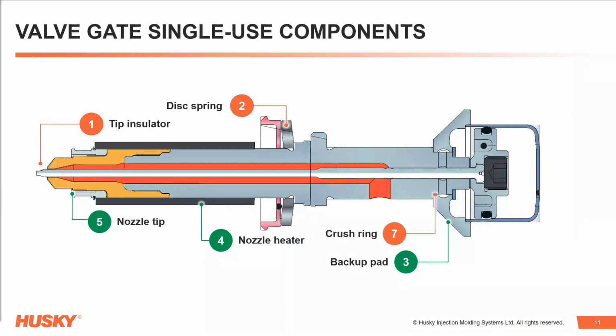The crush ring and the graphoil seal prevent air leaks. These ensure reliable performance for gate opening since excess air leakage can decrease efficiency, and they permanently deform when installed, and they cannot be reused. The piston seal is also a single-use part that should be replaced if removed. This controls the stem actuation in both directions. Age and excessive wear can prevent efficient movement and affect repeatability. So worn piston seals can also prevent the valve stem from completely closing, and that can show up in a part defect that some call high gates or posting.